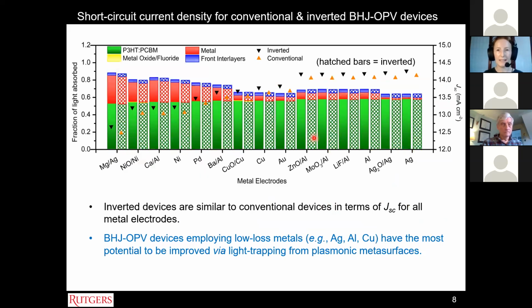So we also looked at the effect of parasitic absorption in these electrodes on the performance of the device, the short circuit current density. You can see as well that many of the metals are actually absorbing a lot of the light, so we call them lossy metals. But if you look at, for example, silver oxide on silver and silver in general, it has the lowest parasitic absorption. So again, as I mentioned earlier, it's the best optical metal as well as being the best electrical conductor. And those go hand in hand. The best plasmonic structure response will be created from the highest conductivity metal.